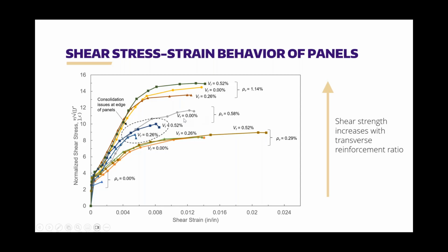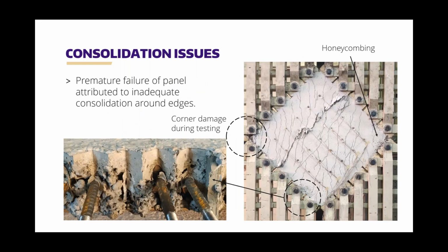And unfortunately, this was the first set of fiber reinforced panels that we tested, and we had some consolidation issues around the edge. And so we're attributing some of that strange behavior to those consolidation issues. And I'll show you what that looks like and why we think that might be the case. So here you see what the edges of those panels look like. Of course, you can't actually tell how bad things are until you take the blocks off at the end of testing. But you can see the honeycombing that's on the outside of that panel. You can see the corner damage that happened during testing, and you can really see the honeycombing on the bottom surface here of the panel during testing.